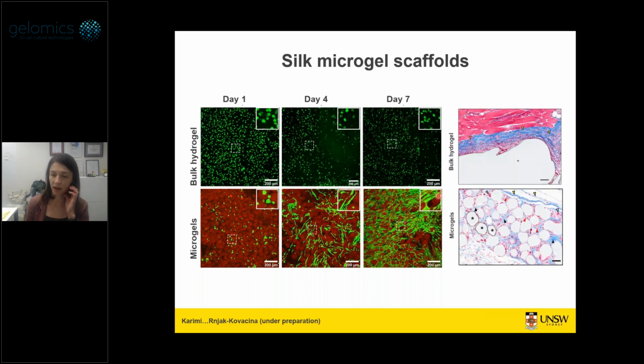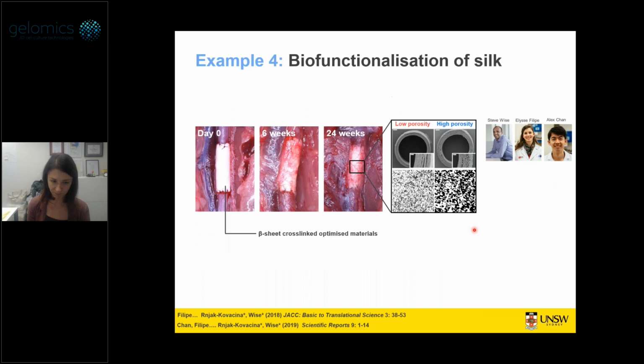And we see a similar effect in vivo. If we implant these, the bulk hydrogels get fibrous encapsulation very, very quickly, where you get this collagen deposition in blue here. But the microgels are getting very little to no fibrous encapsulation, and you're getting all this tissue growth between the microgels, and you get blood vessels growing between them, and you're getting remodeling of this matrix.